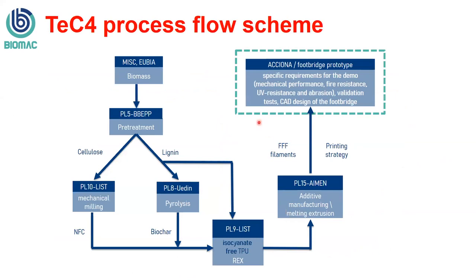And if we look at the process flow scheme here, the idea is that you are taking the biomass, again, pre-treating it and splitting it up into different fractions that you do different things with. So we can take the cellulosic fraction, mill it down to nanofibrillated cellulose, and that of course will give us some mechanical reinforcement for that central honeycomb layer, which is very important. We can take the lignin fraction and directly use this as an additive in this case in our isocyanate-free thermoplastic polyurethane matrix, which is the matrix material for that nanofiller that you see being added in here.